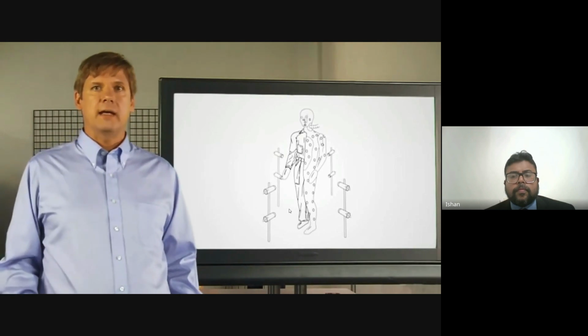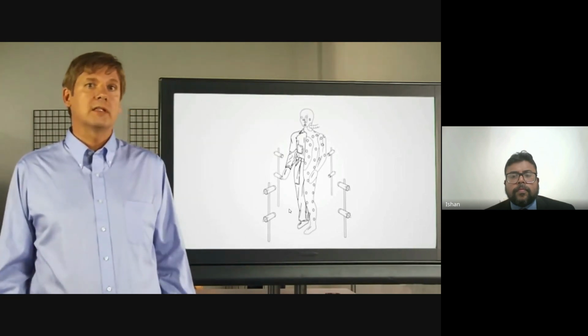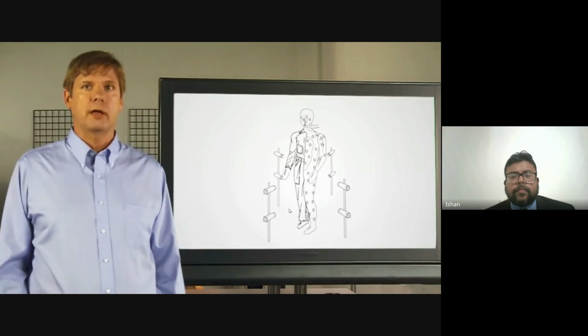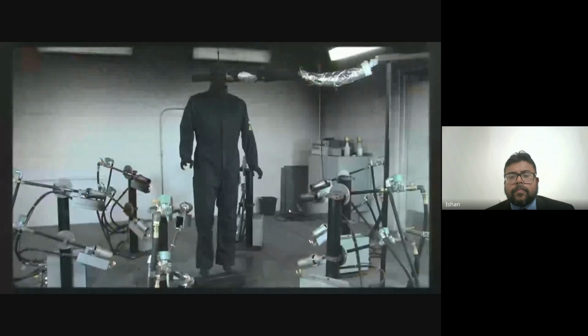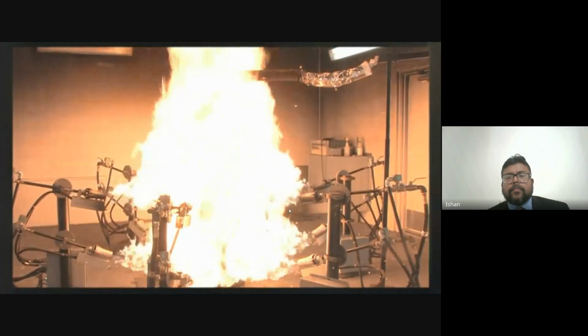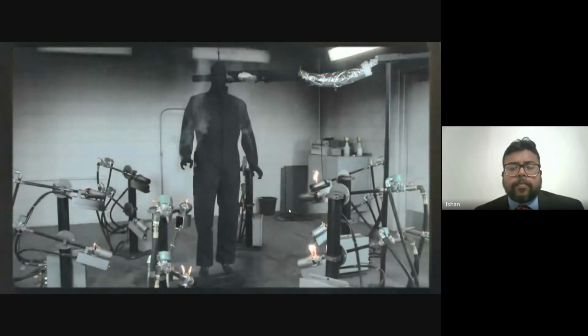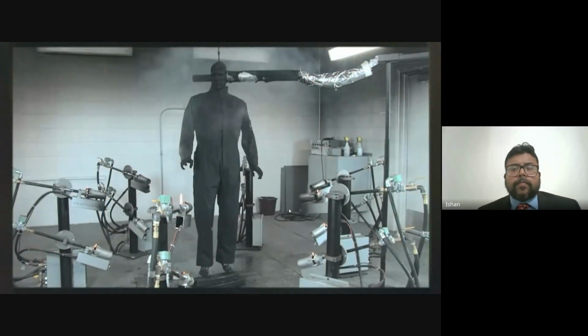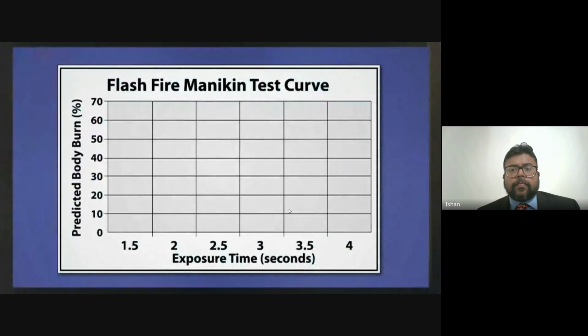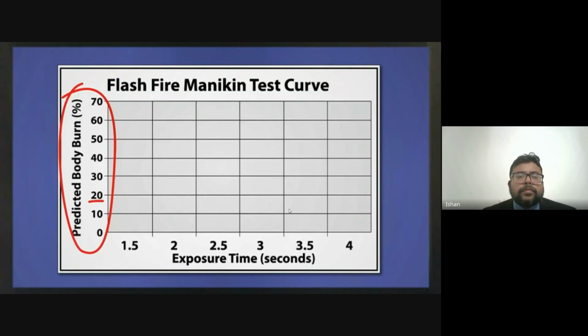Using this collected data, a calculation is made that is used to predict the degree of second and third degree burn injury. Let's see what this looks like. As you can see, the mannequin is totally engulfed in flames for the entire 3 seconds. But once the flames go out, you see the FR coverall has not ignited and does not continue to burn like a comparable non-FR version would. Here is an example of the 3 different burns on the mannequin. Here, you have percentage of body burn, for example, 20% or 40%. And along the bottom is how long the test is run.